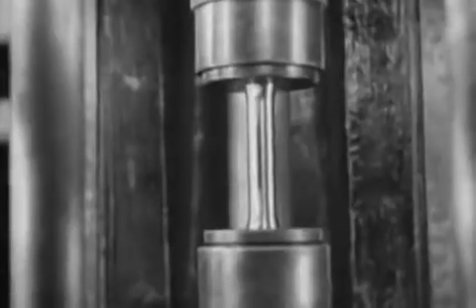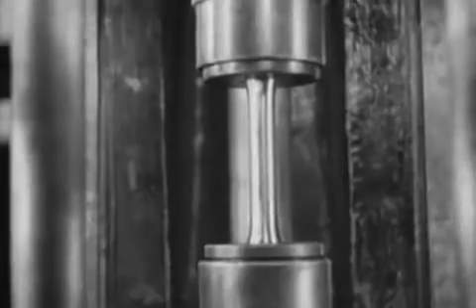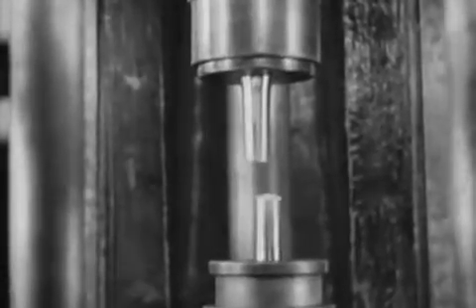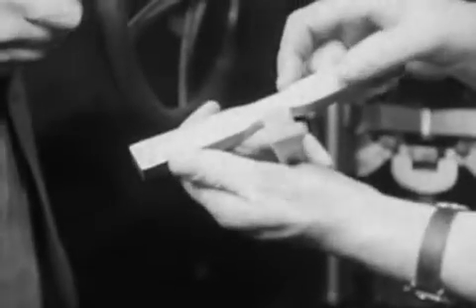From the results of a continuous and thorough examination on these lines of all tire failures, the research department was able to make recommendations about the finish of tire surfaces, which, there is every reason to suppose, will greatly reduce the number of tire failures in service. The new finish for the inside of tires is produced by a tool of exceedingly hard material, and it is considerably smoother than either of the older finishes.